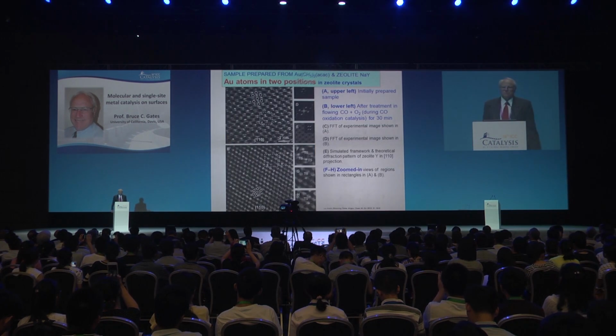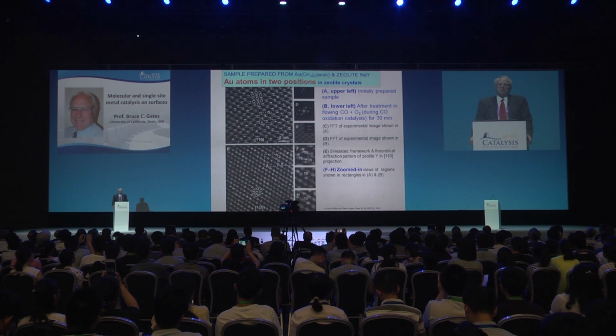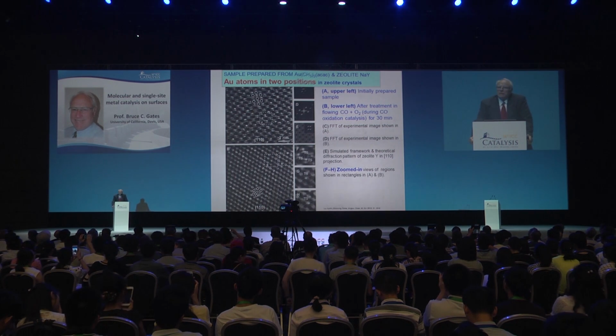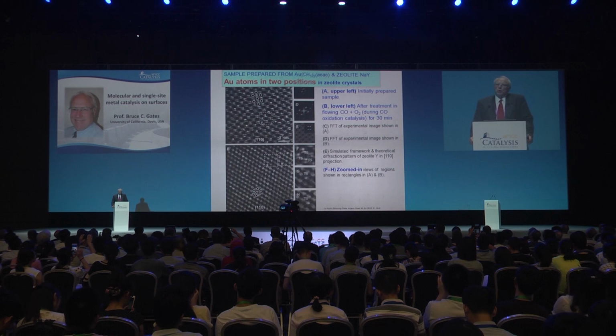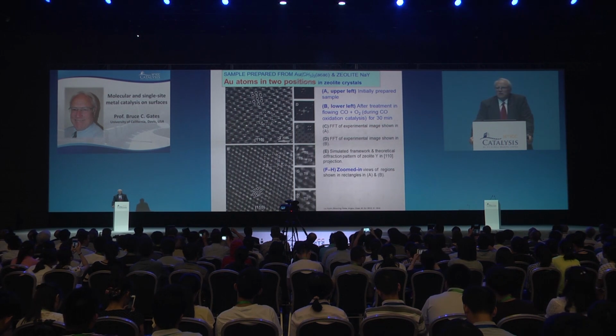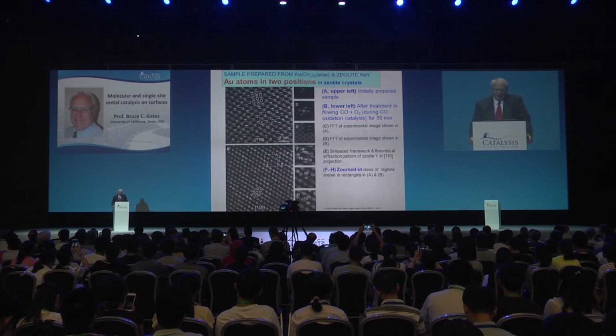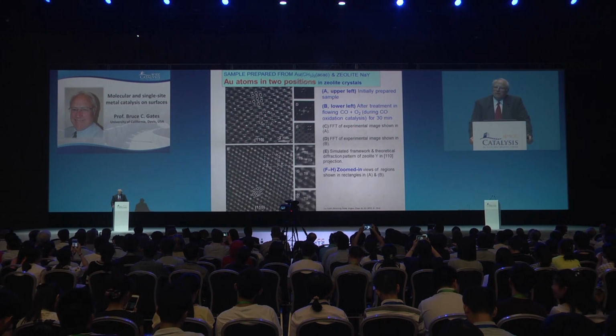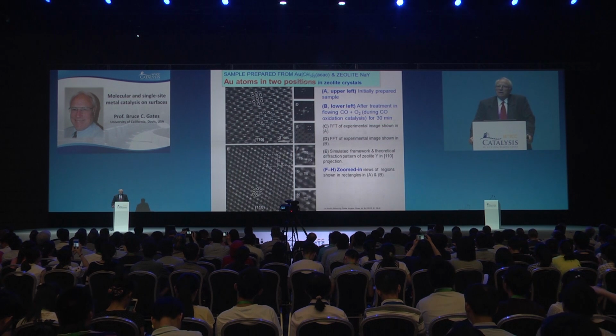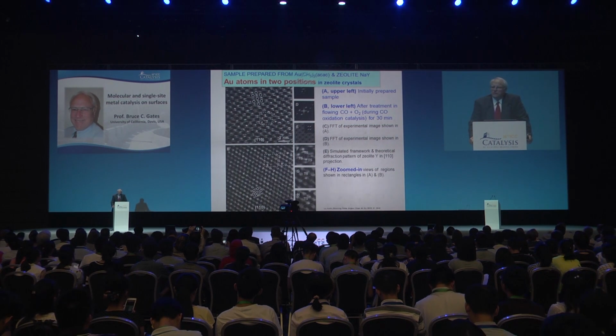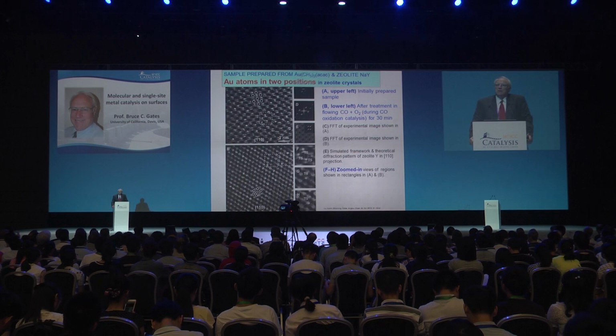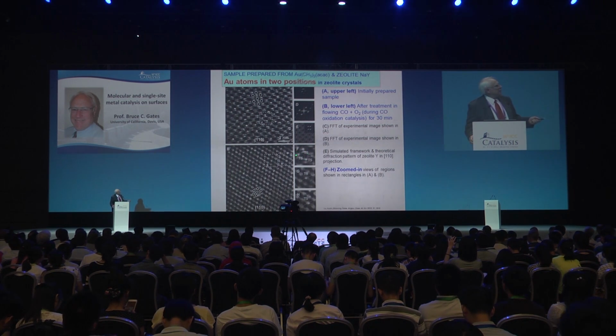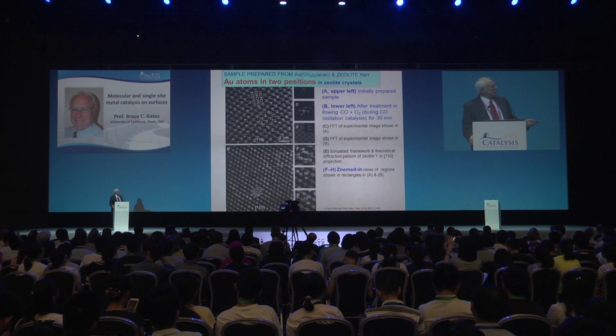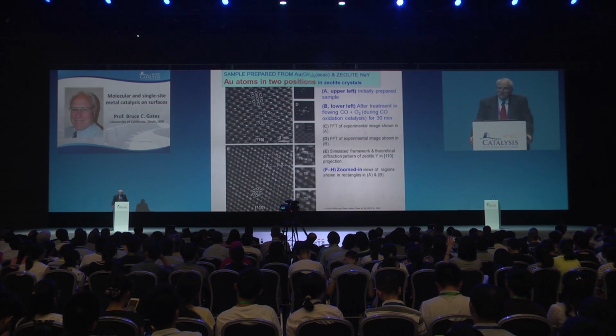I oversimplified a little bit. Here's the image again of the gold on zeolite Y, sodium Y in this case. And what we see looking at the image is that there are in fact two sites within the crystallographically defined structure of the zeolite where the gold resides. So I can show them T5 sites and T6 sites, and they're clearly distinguishable in the images.